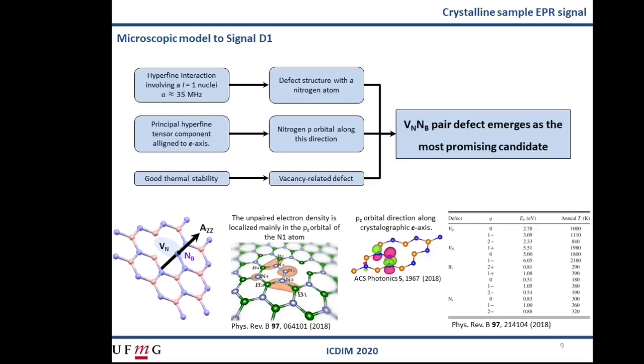So what do we have about the D1 signal until this moment? 1. There is a hyperfine interaction involving a nitrogen nucleus and an electronic spin 1/2. 2. Its hyperfine principal component is aligned with the C-axis. And 3. It has a good thermal stability, persisting through thermal treatments until 550 degrees Celsius. So, theoretical predictions point out that the pair defect VNNB, a nitrogen vacancy next to a nitrogen antisite, obeys these conditions.